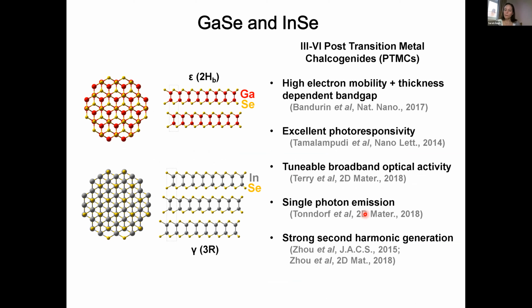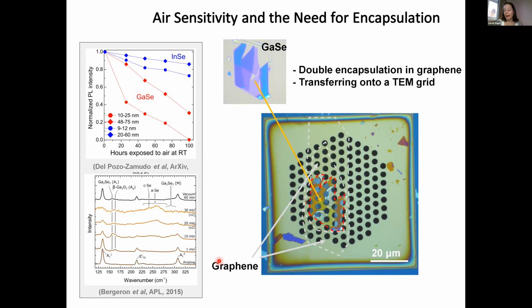These are slightly different from the materials that we might be very familiar with as 2D materials, because they have two metals, a sort of double metal layer sandwiched between these two layers of chalcogens. And that's what we can see here. Again, we get both the 2H and the 3R type stacking. So if we have a look at these, we've seen that they do degrade. They degrade quite quickly as a function of time, certainly over hours when exposed to air.